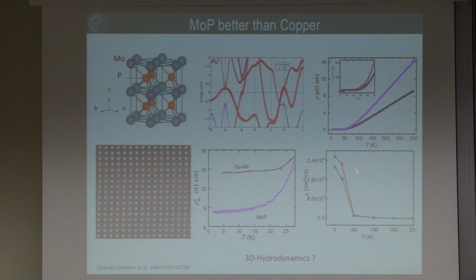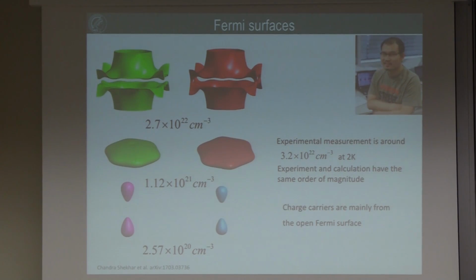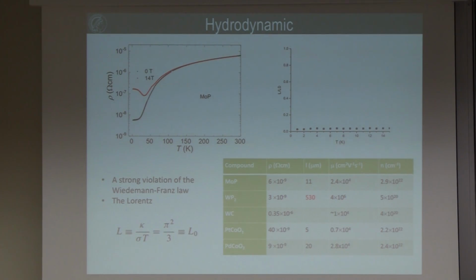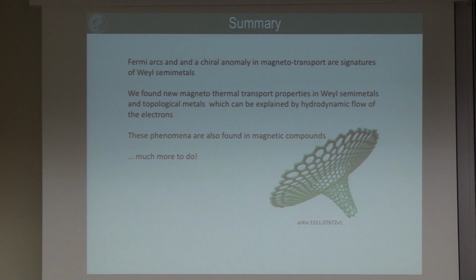We find still a Hall effect, which gives us a kind of high electron mobility, and we find a magnetoresistance effect which is not as pronounced. It's very similar to PdCoO2, and in this range we also have violation of the Wiedemann-Franz law, etc. So there might be more materials which have this giant magnetoresistance effect, which we can explain with hydrodynamic flow.